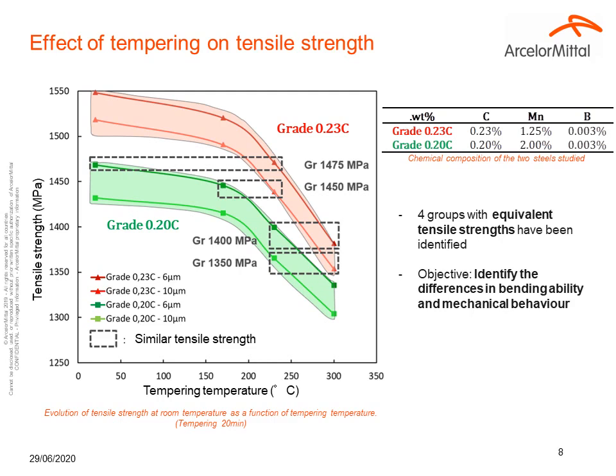For all the conditions, there is a slight decrease of tensile strength up to tempering at 170 degrees Celsius, then it decreases sharply. We identify four different groups with almost the same tensile strengths, but from different materials and from different tempering temperatures. The goal is to determine the variation of the crash ductility with the same tensile strength. We are now going to compare mechanical properties group by group.